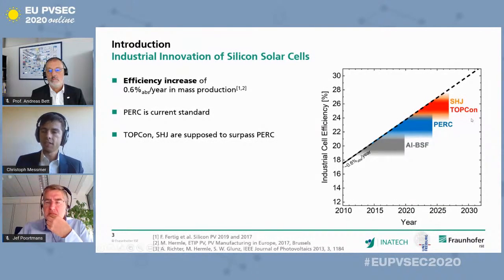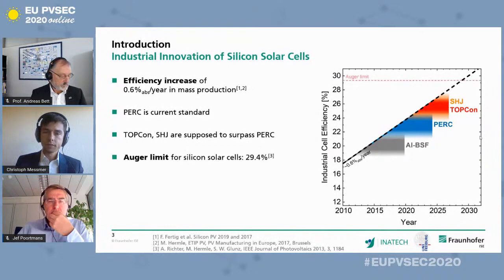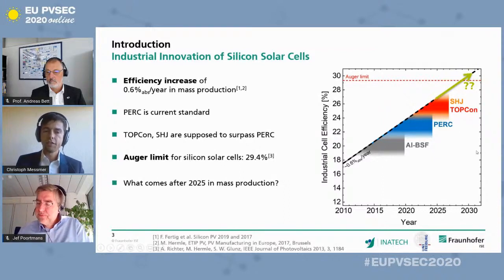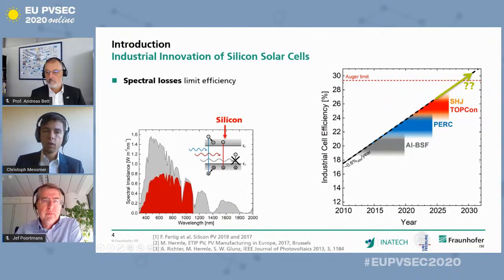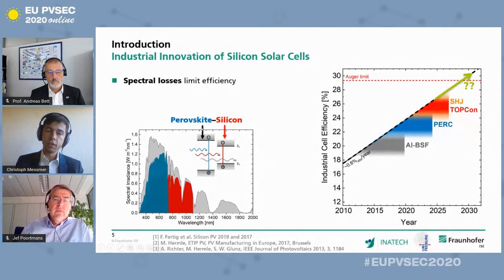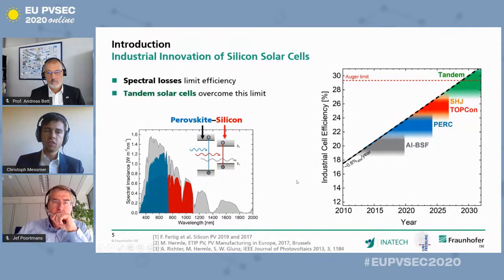Passivating contact technologies like TOPCon and silicon heterojunction are supposed to surpass this technology in the future. However, there's a fundamental Auger limit for silicon solar cells of roughly 29%. So the question arises, if we want to keep this trend, what comes after, let's say, 2025 in mass production? And for this, we have to look into the physics where spectral losses limit the efficiency. Here you can see the spectrum of the sun in gray, and the silicon can only use the red part of the spectrum. But if we use a second higher bandgap material, for example, perovskite, we can more efficiently use the blue light of the spectrum. And this so-called tandem solar cell can overcome this barrier of 29%.